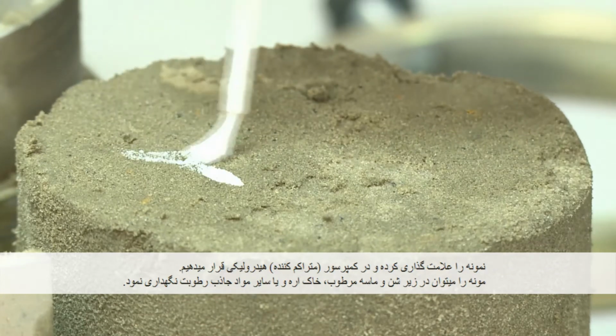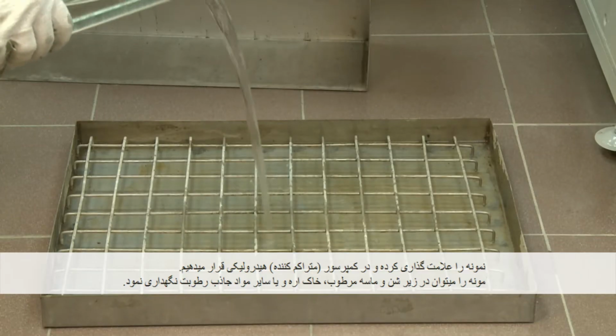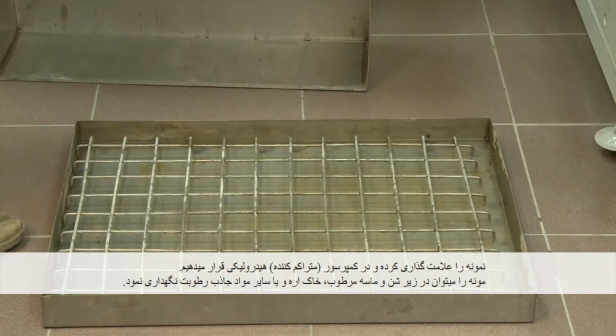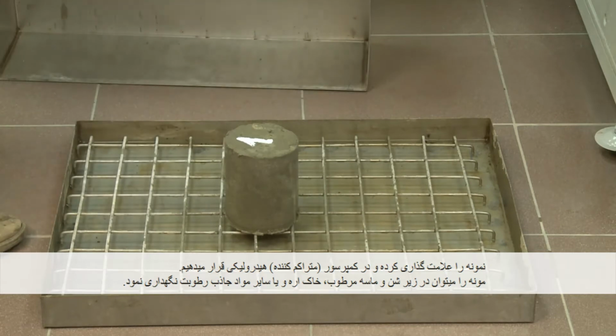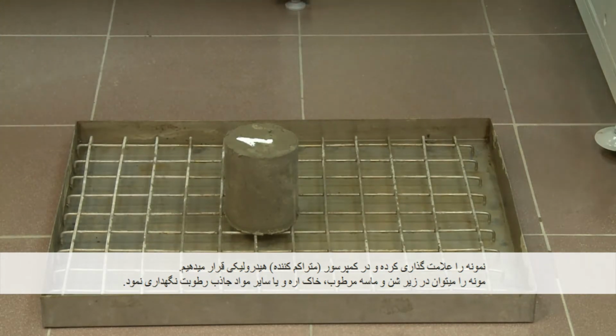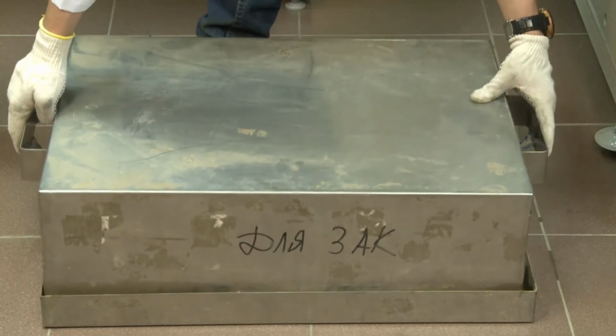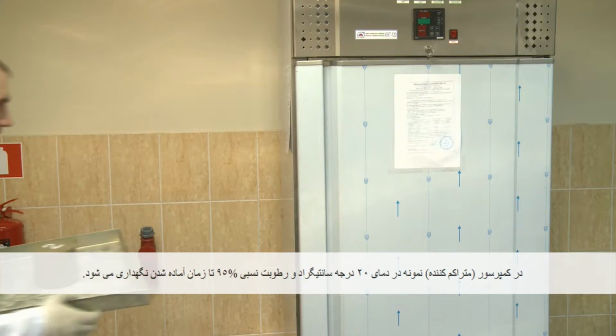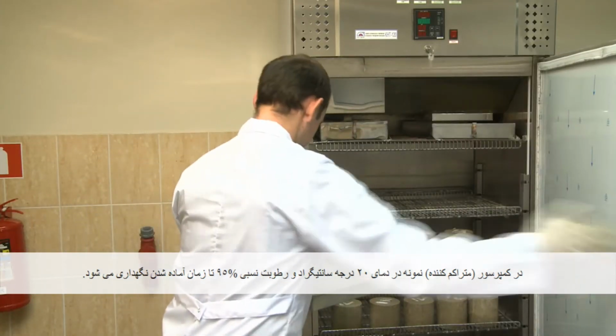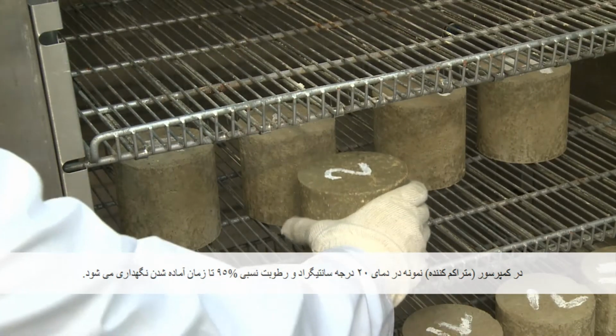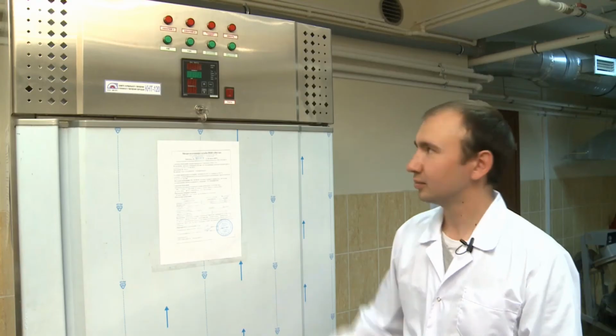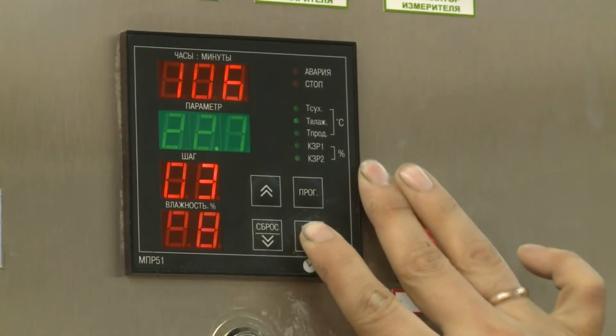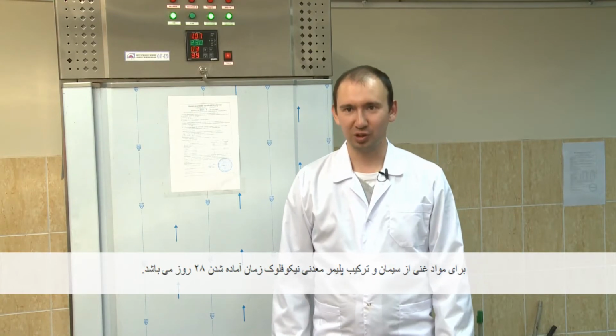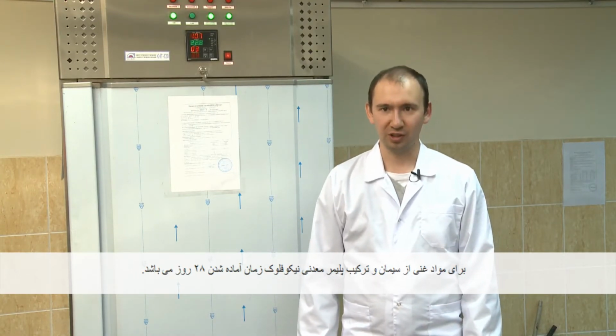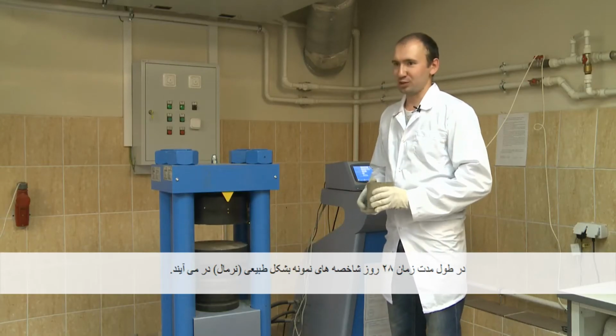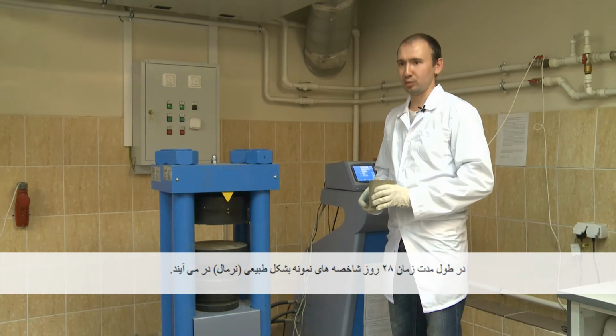Now we attach labels to samples and place them into the humidity chamber with a hydraulic lock. It's allowed to store samples under layer of wet sand, saw dust and other regularly wetted hygroscopic materials. Samples are stored in the humidity chamber at 20 degrees Celsius and 95% relative humidity till it reaches the designed age. The design age of materials improved with cement and mineral polymeric compound Nikoflok is 28 days. Rated parameters of samples are determined upon expiry of 28 days.